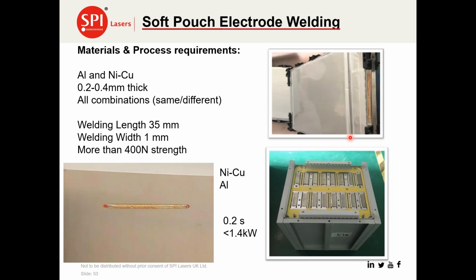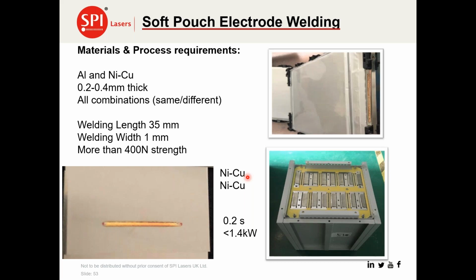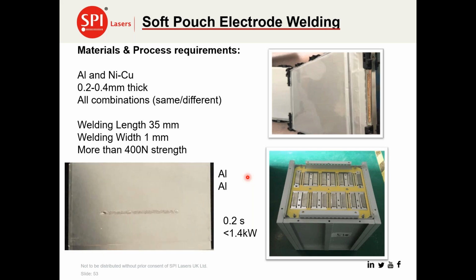And again, on soft pouch electrode welding, here the requirements, again, it's like the stuff that I showed earlier, using the nanosecond processing, where we were looking at individual spots. Here we're talking about lines of weld, and there's various combinations from nickel copper to nickel copper. Again, all of these welds, we're talking about 35 millimeters, done in about 0.2 of a second, with a 1.5 kilowatt laser operating at less than 1.4 kilowatts on the workpiece. Very high strengths are achieved.